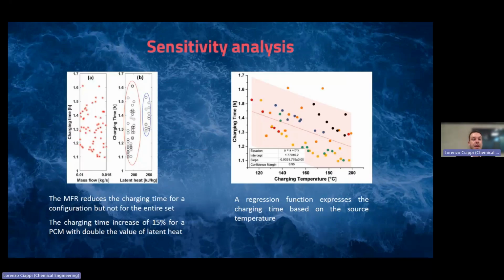Another parameter is represented by the mass flow rate. The mass flow rate of the heat transfer fluid has a limited effect on the operation of the system. Indeed, if we consider the entire set of the configurations analyzed in the study, a strong correlation between the mass flow rate and the charging time was not found. However, it has to be remarked that, fixing the configuration of the system, a variation of the mass flow rate of the heat transfer fluid has an effect on the time required for the charging and discharging of the system.